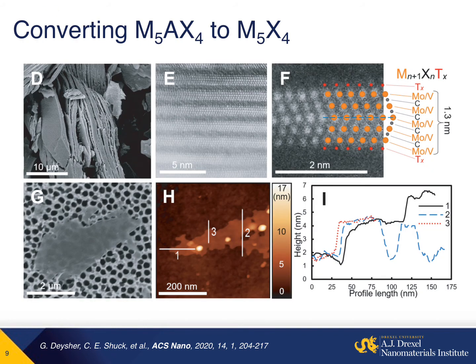After etching, we again examined this material using an SEM. Instead of the close-packed layered structure that we saw with the MAX phase, we instead see that the layers are pulling apart in an accordion-like structure. This is very indicative of using high concentrations of HF to etch, and very indicative of what multi-layer MXene looks like. If you zoom in on any of these sheets, you will see that the A layers are completely removed, and the MXene sheets are just being held together by van der Waals forces between the sheets. Zooming in even further, you can see that this twinned herringbone-like structure is maintained in the MXene, and moreover, the surface terminations are above here.